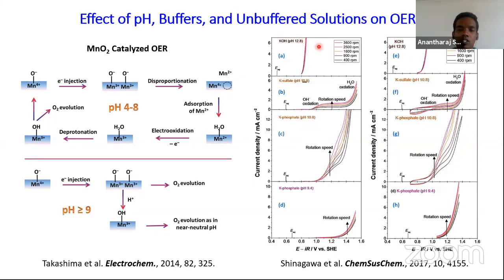As you can see, at high pH, 12.8, this is 0.1 molar KOH, where we don't have any issue of having a sufficient number of hydroxide anions for an easy oxidation of water. So increasing rotation per minute is not affecting the performance at all, which means that at higher pH, when the electroactive species, the hydroxide, is high in abundance, its diffusion does not matter at all. But in the case of low pH solution, we can have two different reactants, we can have water molecules and we can also have sparsely present hydroxide anions.